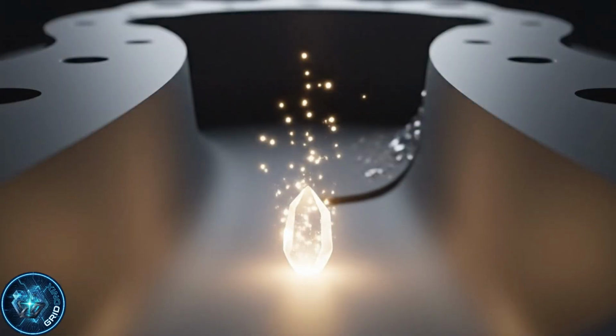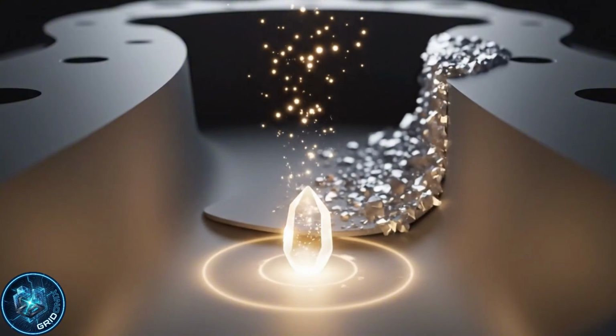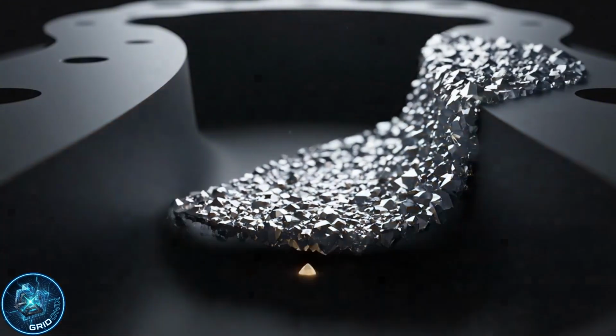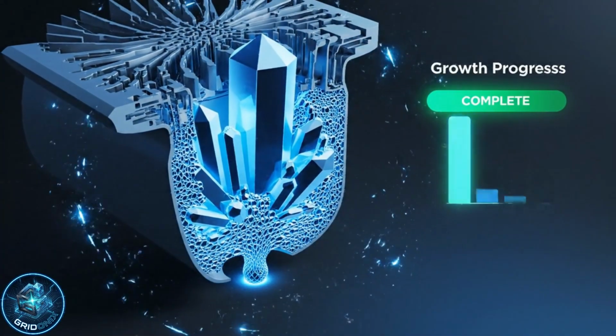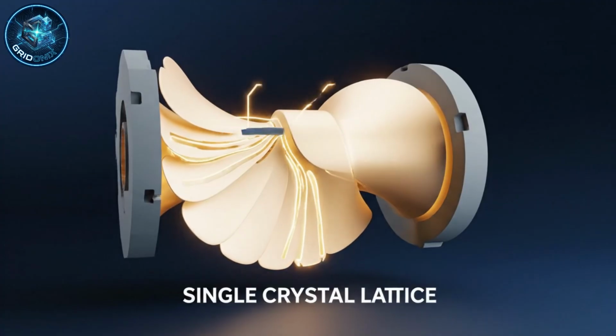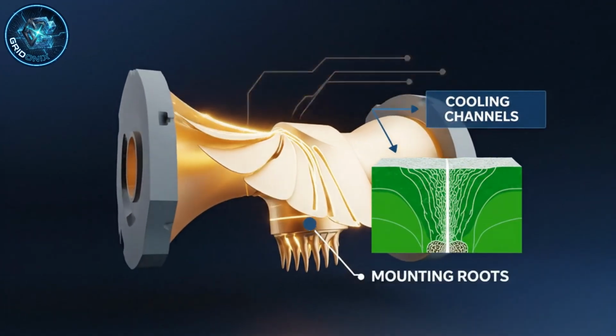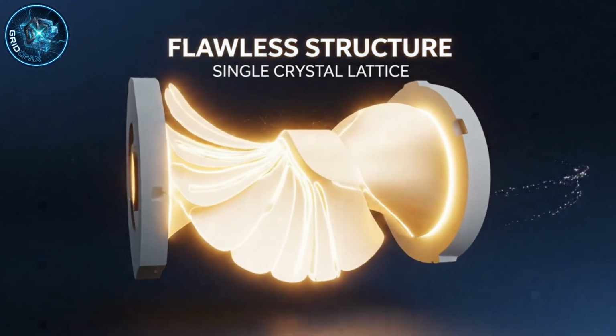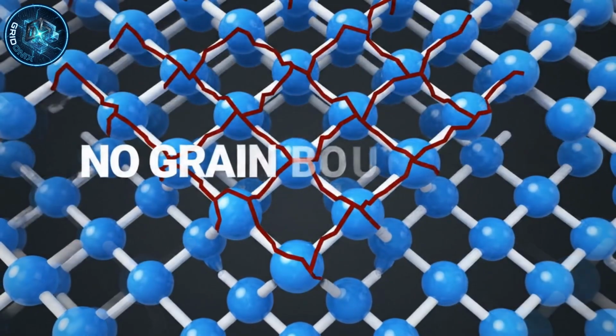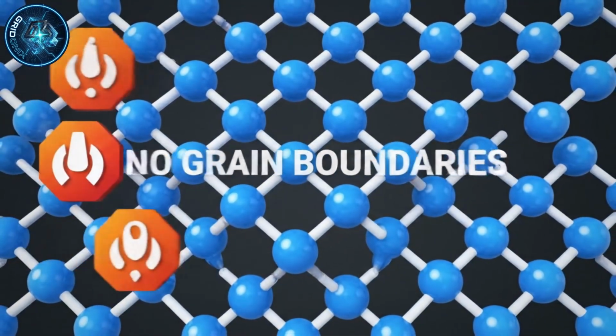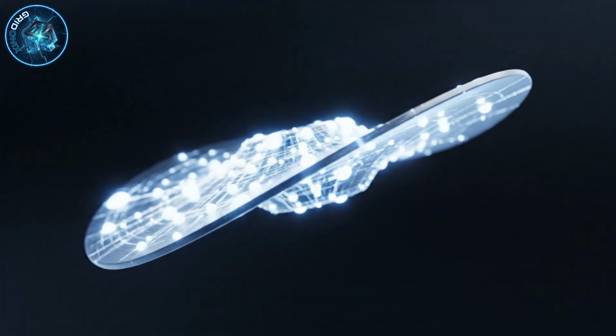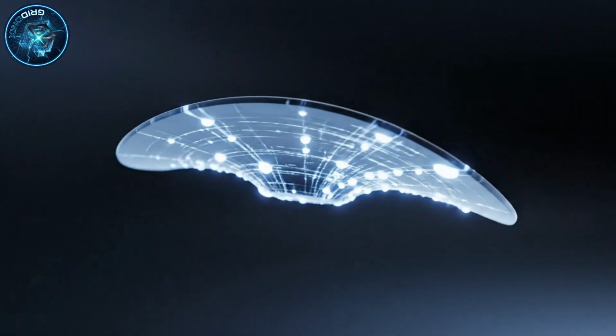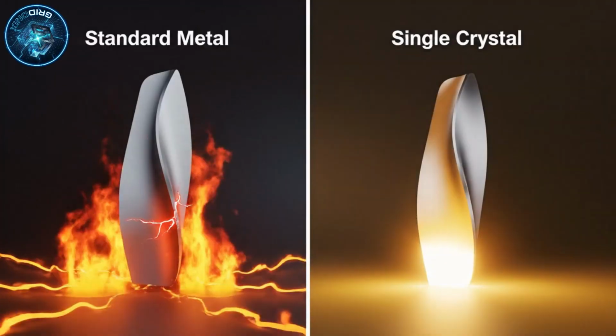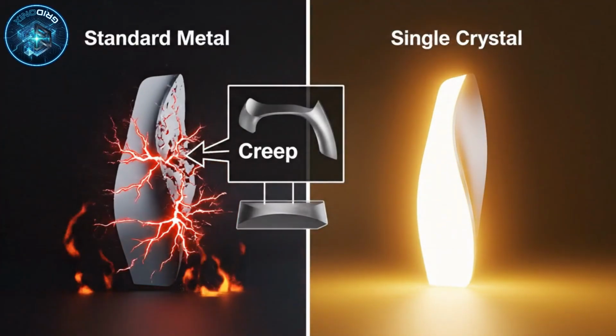This single survivor emerges into the main cavity of the blade mold. As the mold continues to lower, this one crystal acts as a seed. It grows, it expands, it fills the entire void. The entire turbine blade, every curve, every internal channel, every mounting root, solidifies as one single crystal. There are no grain boundaries. There are no microscopic weak points for the heat to attack. This single crystal architecture gives the blade immense strength against creep, allowing it to survive temperatures that would tear a standard metal apart.